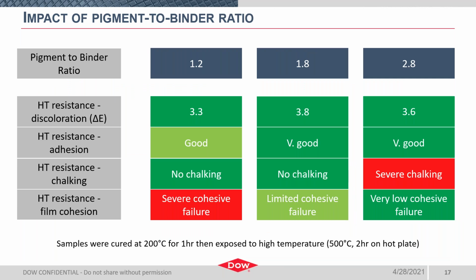Another formulation parameter we dove into was PVC. As we know, this has a direct impact on paint performance. To simplify here, I show variation in pigment to binder ratio from 1.2 to 2.8, with 1.8 as our relative chosen midpoint. And for all formulations, we assessed color change, adhesion, chalking, and film cohesion after the high temperature exposure. The left column shows performance for the lowest pigment to binder ratio tested, 1.2, the middle column 1.8, and the right column is your highest pigment loading level with a pigment to binder ratio of about 2.8. All the test specimens, again, were cured for an hour at 200 C, followed by that 500 C exposure on a hot plate.